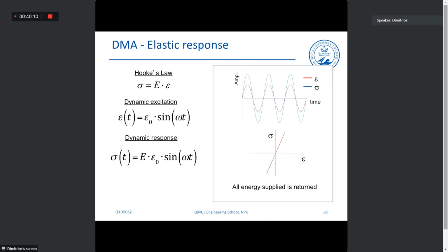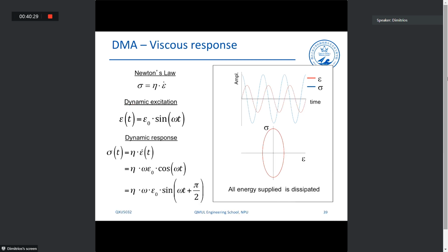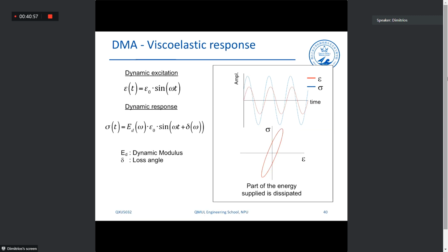Yes, this is what we said about the elastic response again, and how it's reflected in the DMA. As we can see, we provide dynamic strain and we obtain dynamic stress. They're both sinusoidal, so they are in phase. In viscous response, we can see that these are out of phase. You can see that the difference in the phase is 90 degrees here for a viscous material. So all energy that is applied is dissipated. And finally, for the viscoelastic material, we have a part of the energy that is applied that is dissipated.